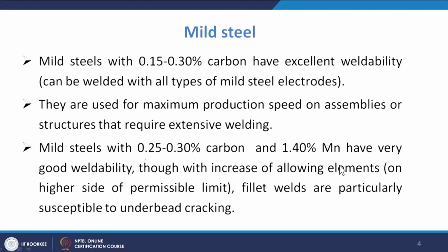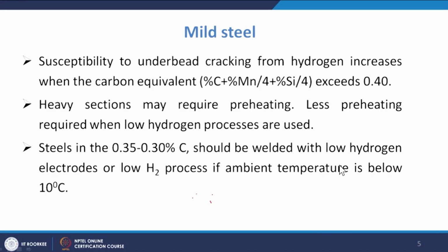With increasing alloying elements on the higher side of the permissible limit, the fillet welds are particularly susceptible to underbead cracking. Next, coming to the susceptibility to underbead cracking from hydrogen, it increases when carbon equivalent exceeds 0.4 percent. Okay, so heavy sections may require preheating.